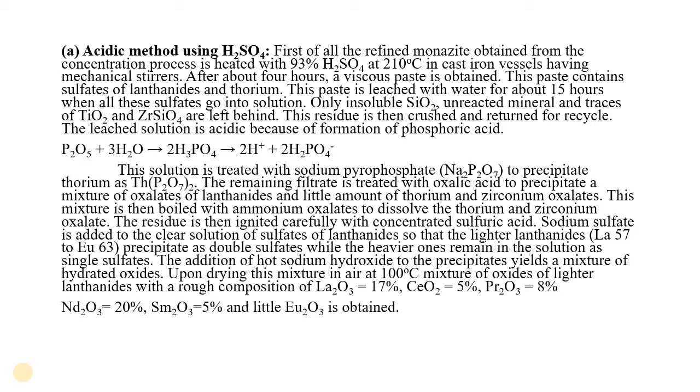Only insoluble sand, SiO2, unreacted minerals and traces of titanium oxide and zirconium silicate are left behind. It means these are the residues. The soluble portion goes into the filtrate, which passes through the filtering medium. This residue is then crushed and returned for recycle.